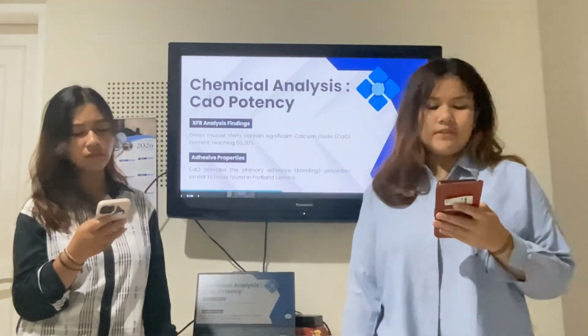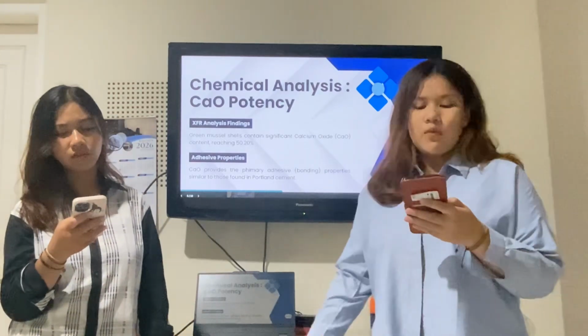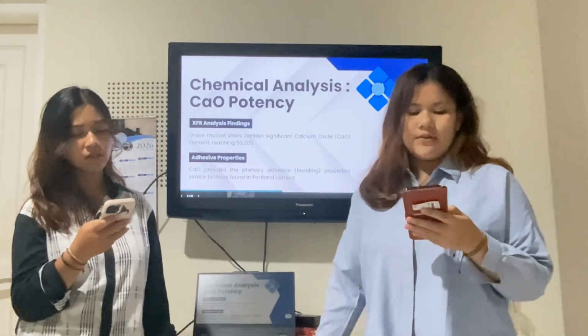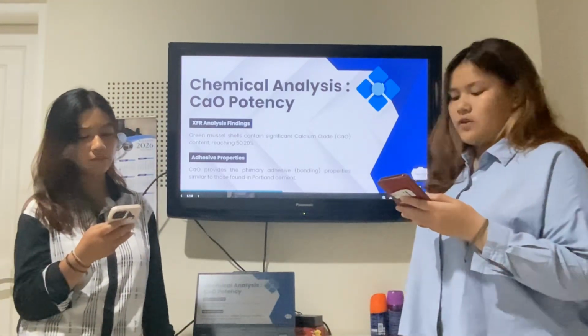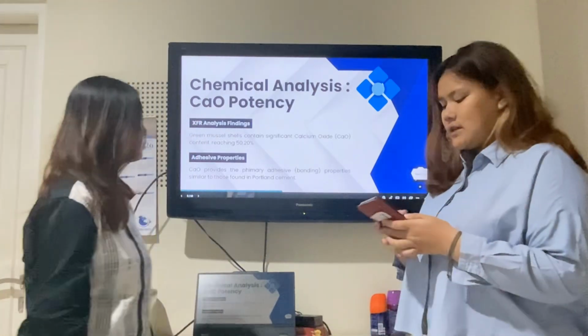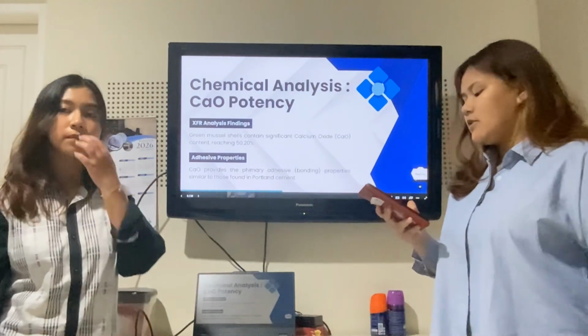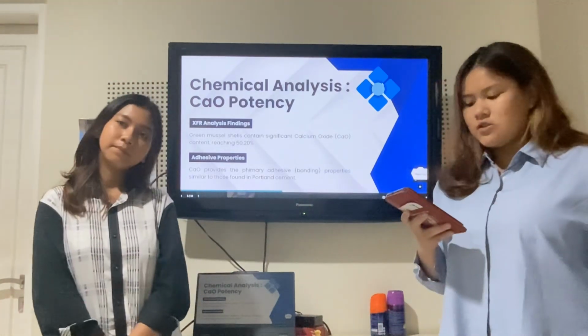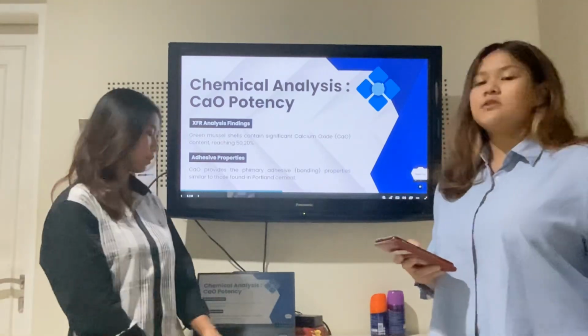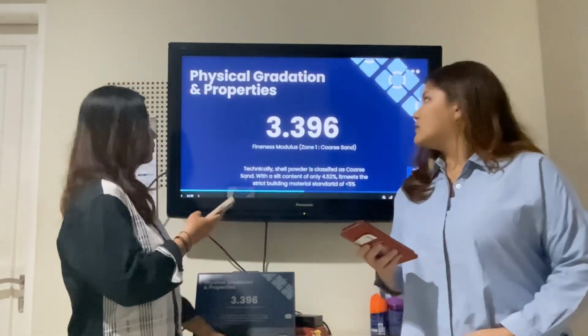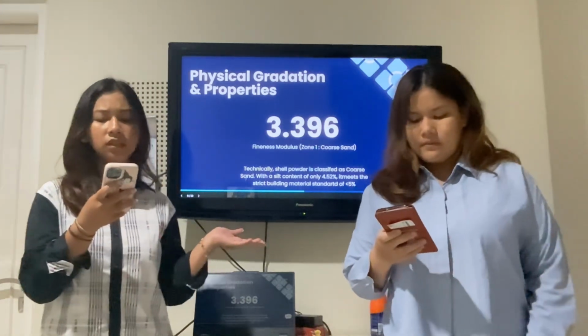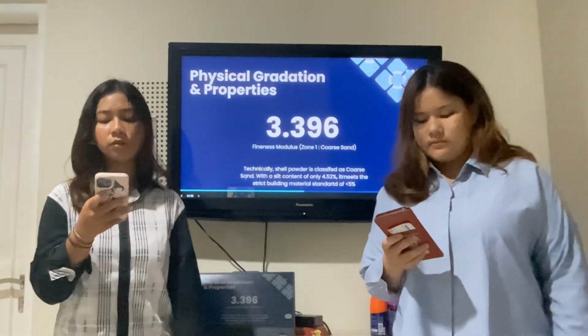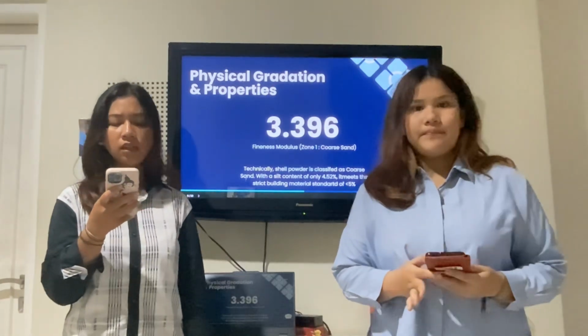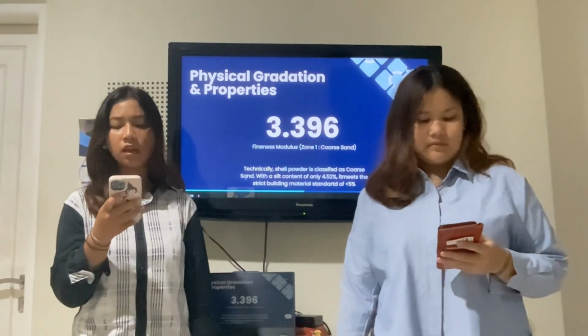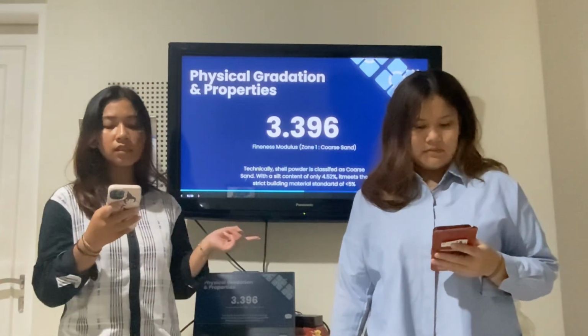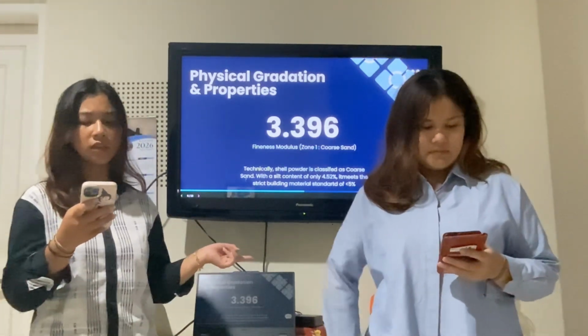To understand why this works, we look at the chemistry. Our XRF analysis shows that green mussel shells contain over 50% calcium oxide. Chemically, this is very similar to Portland cement, providing the necessary bonding properties to hold the paving block together. Physically, we process the shells into powder. The result, a fineness modulus of 3.396, which classifies it as zone 1 coarse sand. This is the perfect texture for a filler material in concrete mixture.